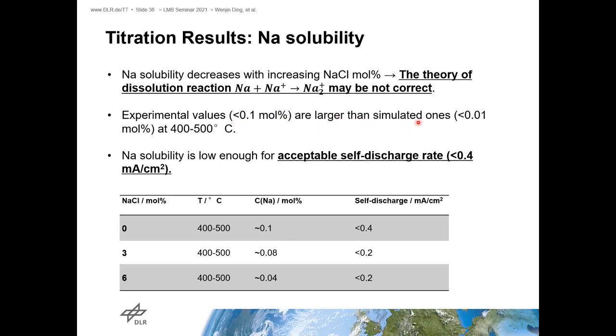Yeah, it's larger than the simulated values, but it's low, and the estimated self-discharge rate is below 0.4 milliampere per square centimeter. And then we can have such conclusions. For the selected molten salt electrolyte, the sodium solubility is low enough for an acceptable self-discharge rate. So we can use this molten salt electrolyte for the battery test.